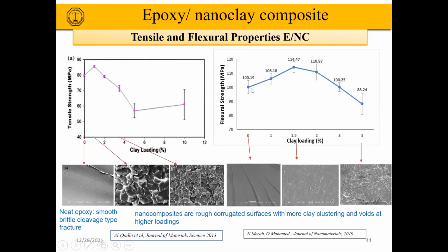Once you have this mixture of intercalated and exfoliated structure, you can see the effect of the addition of nanoclay on your tensile strength. For example, here with 1.5 or 1% of Nanomer addition, we have increased the tensile strength by about 10 or 11%. After that, once you go beyond 1.5%, it starts to decrease.